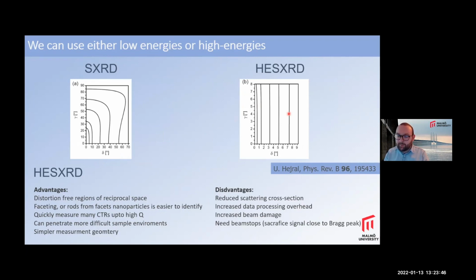And this is a paper of Andreas's, also Uta, and you can see that this shows the curvature of CTRs at various positions on a detector at low energies, and this shows it at high energies. And you can see that at high energies the CTRs are almost straight. So this makes analyzing them and immediately interpreting them a little bit simpler.